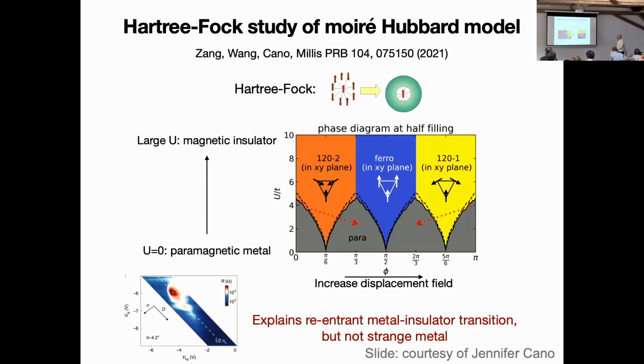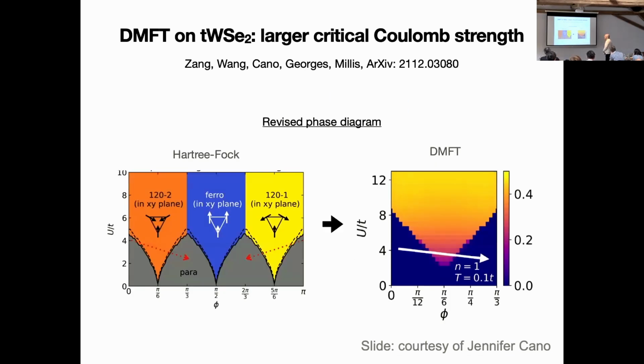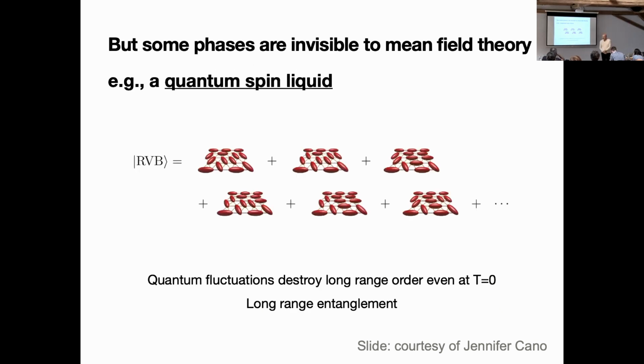So the next thing you can do is study this problem with dynamical mean field theory. You shouldn't expect from this to be able to describe the spin liquid phases, at least not in the single-site DMFT picture, but you can get a much more precise estimate of these transitions. And you see here how the critical U for the ordering transition was displaced by about a factor of 2 when you go from Hartree-Fock to DMFT. So that's something that we did with the same people that I mentioned before, and I'm very grateful to have been associated to this work.